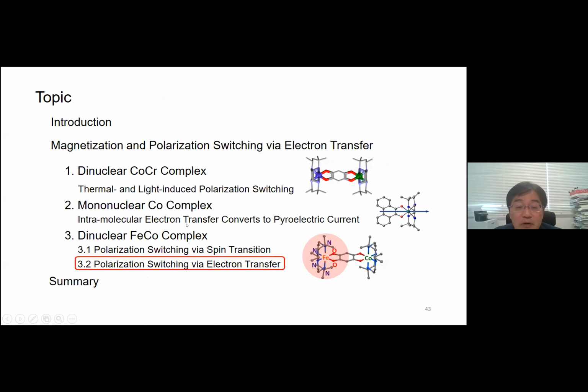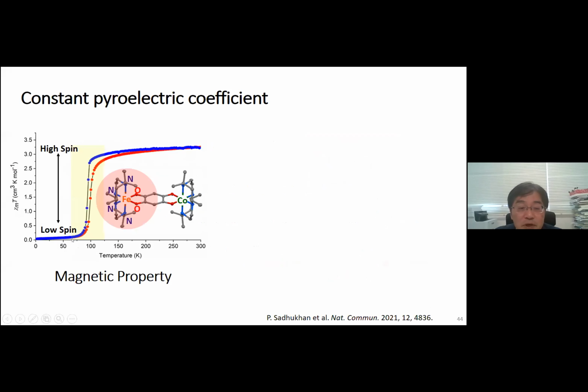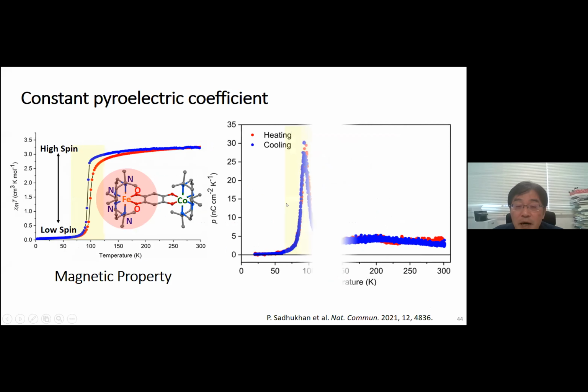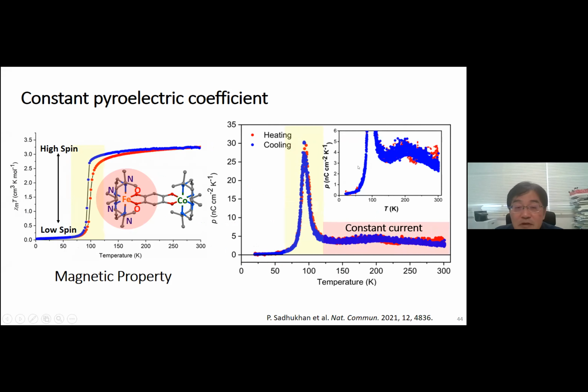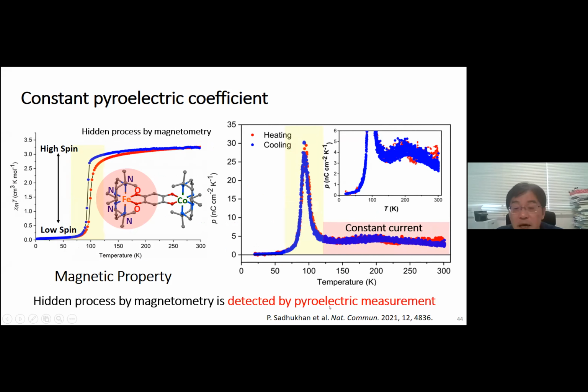And furthermore, we observed interesting polarization switching behavior above the spin transition temperature. As I mentioned, this complex exhibits spin transition here, and above and below the spin transition, there is almost no change. However, when carefully looking at the pyroelectric property, we detected nearly constant current. And this is an expanded view. So this is a hidden process by magnetometry, but it is detected by pyroelectric current. And this process should be accompanied by a polarization change.